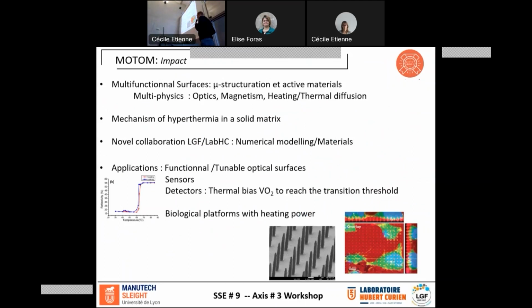In terms of impact of that project, as you can see, the project is related to multifunctional surfaces with a combination of microstructuration and active materials. It relates to multiphysics in terms of optics, magnetics, and heating and thermal diffusion. In terms of impact, also, it is interesting to study the mechanism of hyperthermia in a solid matrix. At the moment, in the community of hyperthermia, there is a large debate about the temperature of the nanoparticles. It is clearly not the same when you are in a liquid and when you have these nanoparticles in, for example, a biological cell. So it is important to have some model situation, and the solid matrix is a good model situation to understand how much is this increase.